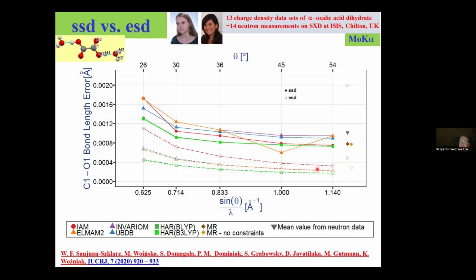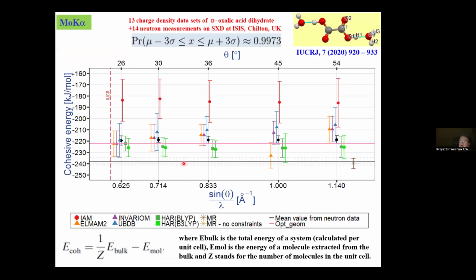And as we can see here, the smallest estimated standard deviations are, of course, for Hirshfeld atom refinement, but also the smallest sample standard deviations, resulting from multiple refinement, from multiple data sets, from repetition of measurements many times, are also for HAR. And so when you are getting ESDs from your refinement methods, please remember the true errors are bigger, at least 2 times bigger than those you are obtaining from the least squares method. And does this matter?